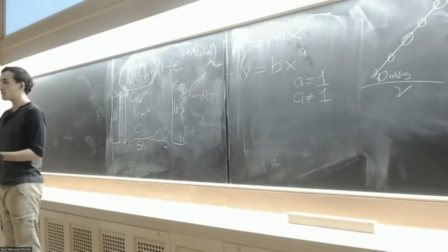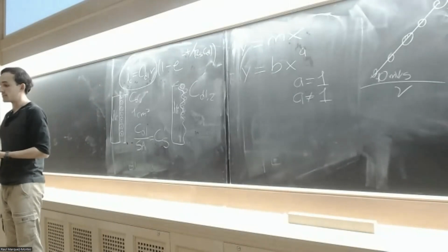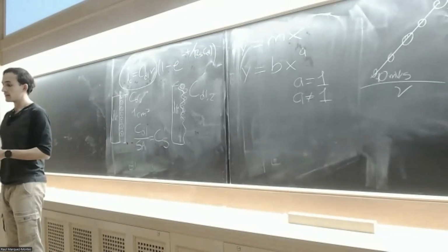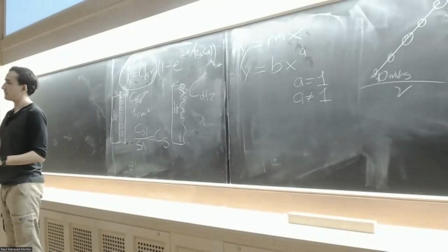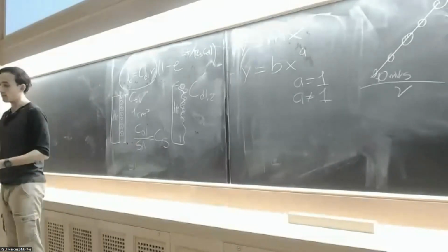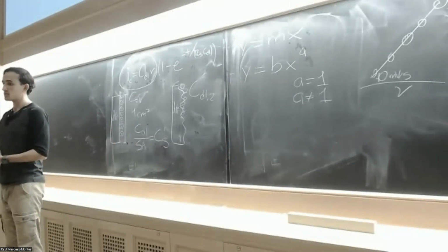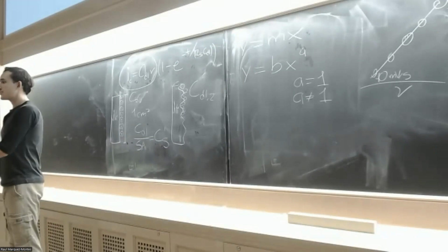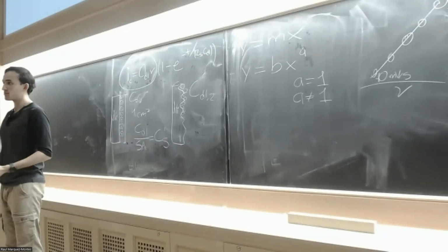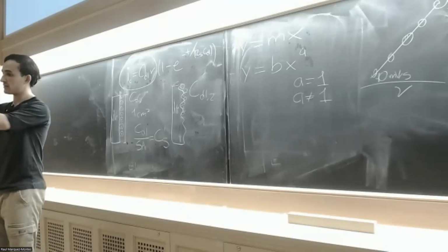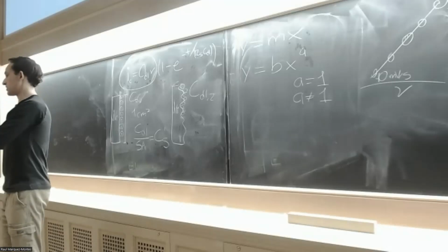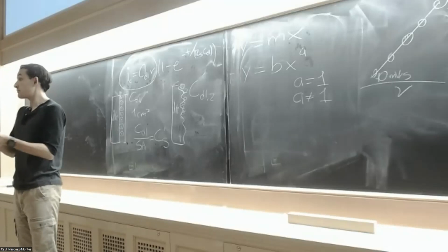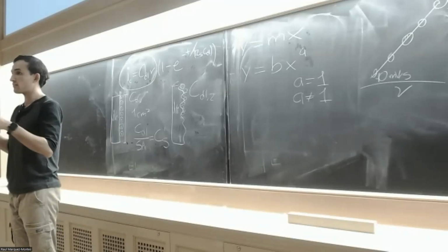However, if you do that, you may oxidize or reduce whatever you have in your sample, so you may change the composition. So an easier way to do it is just to measure the open circuit potential. The open circuit potential is basically the potential where no reaction happens. It's like the equilibrium potential. And the way you measure it, actually you can use a multimeter. You don't need a potentiostat, you don't need anything like that. You can just put each terminal to each electrode, and the potential that results there is the equilibrium potential of the system, because there's no current